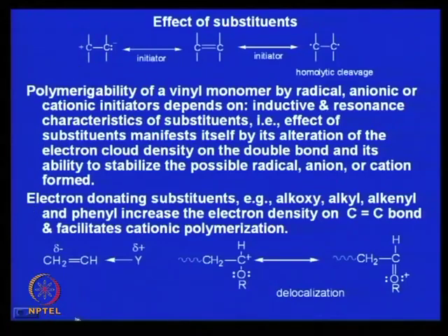That depends on, look here, suppose a Y substituent attached to this carbon. Now, if this has the capability of electron donating nature to this pi electron, that will increase the electron density in the pi bond between these two carbons, or else it can decrease the electron density by withdrawing electron.